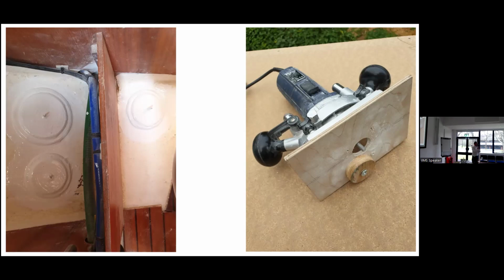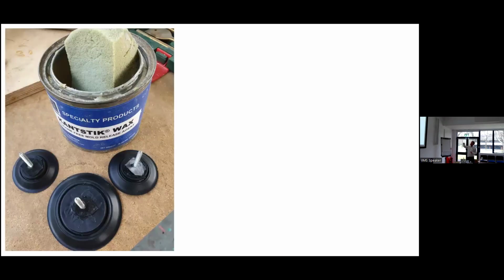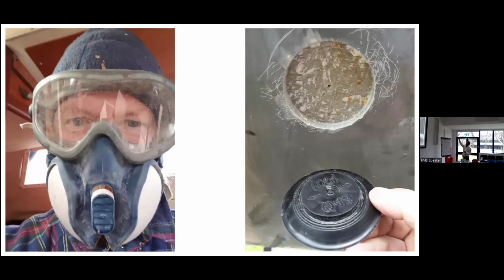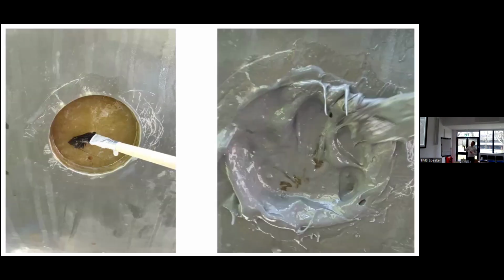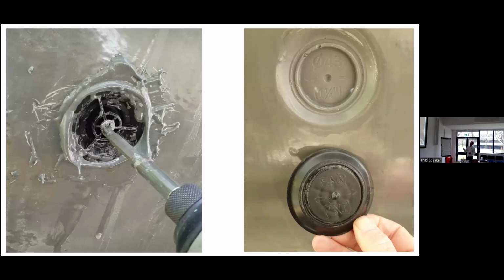So I had some heat lamps, I cured this well. But the other thing about epoxy repair, if you're going to gel coat over, it has to be abraded scrupulously. I think scrupulously is more thorough than thorough. It should be 80 grit, really, really thoroughly. On the next slide, you see what I did on the outside of the hull. I just prepped up these plugs. And on the next slide, you can see I rebated the hull, wearing appropriate PPE gear. Then you can see that I set those plugs against a pigmented, thickened epoxy mix. And the next slide, you can see how they work. So I secured them with a self-tapper and then just released them, and they leave that impression in the hull.